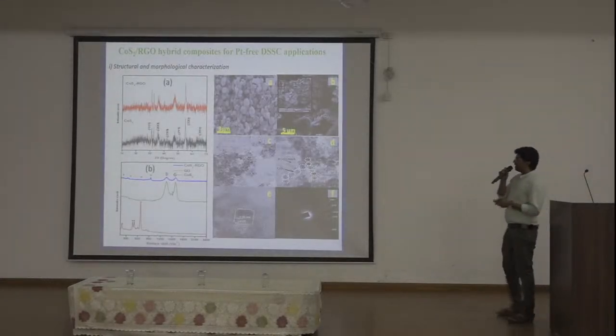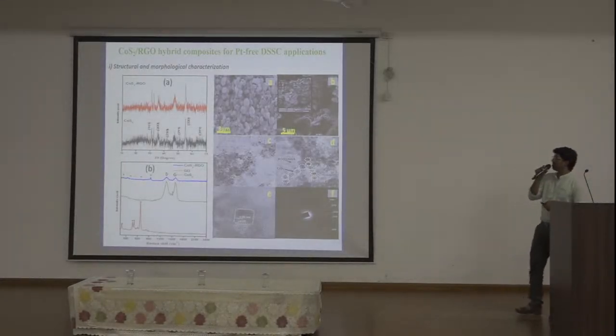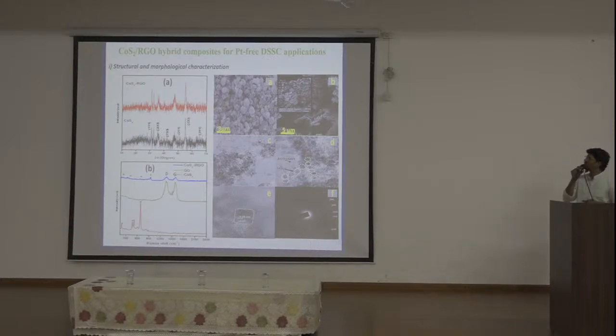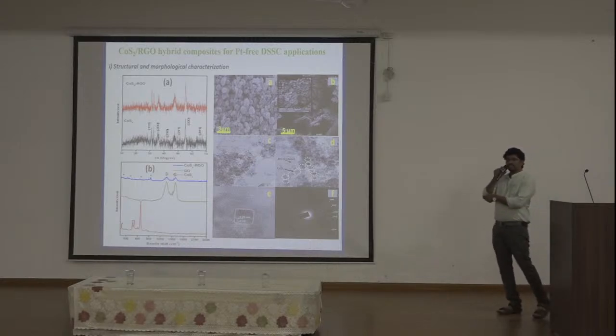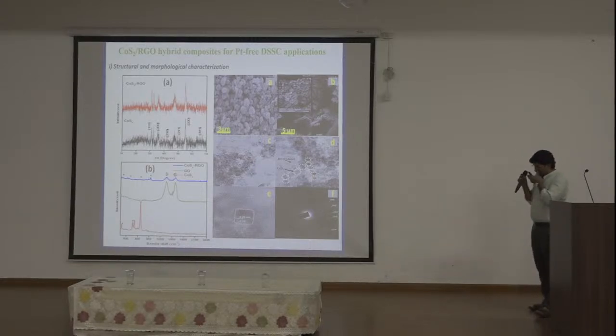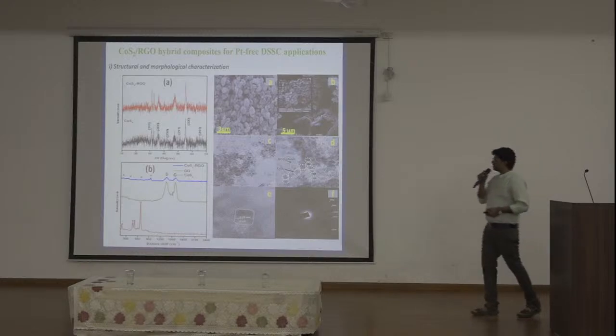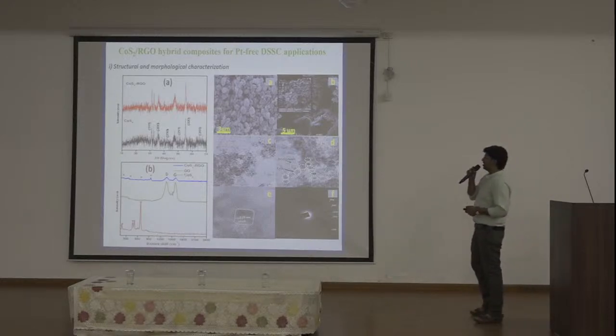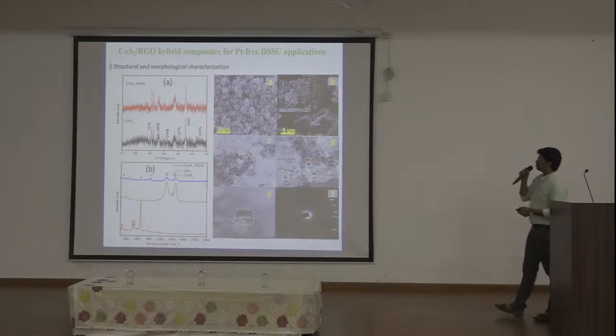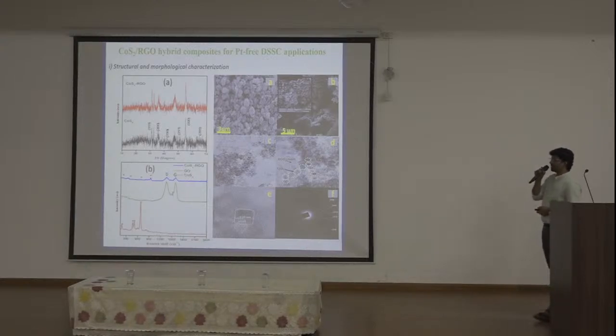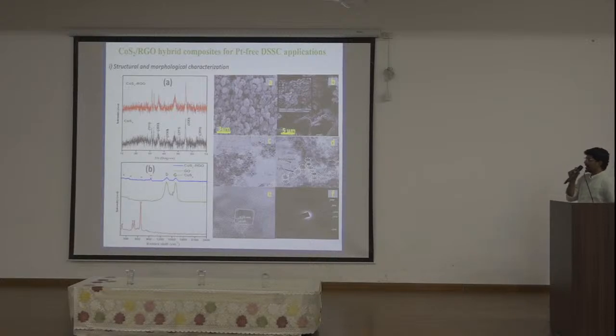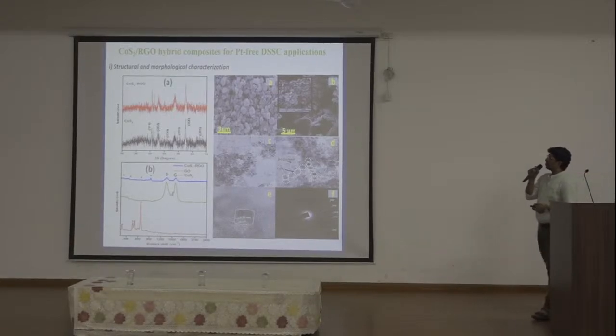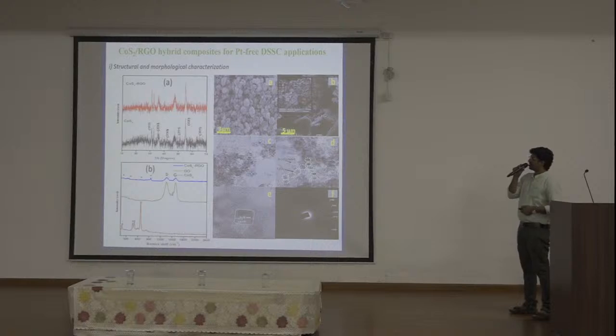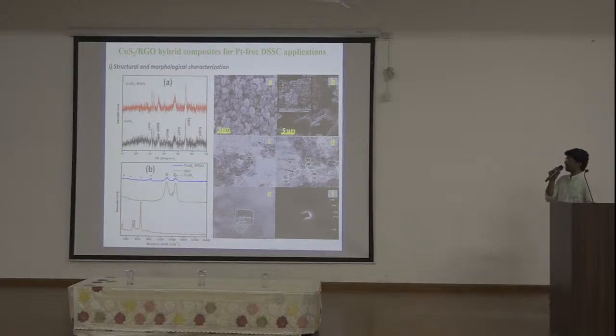So based on this, we have designed a cobalt sulfide and RGO hybrid composite counter electrode as an alternative for use in DSSC applications. From the basic characterization, the XRD shows planes 111, 200, and 210 corresponding to the cattierite structure of cobalt sulfide. After inclusion of graphene oxide, there is no change in the XRD spectrum.